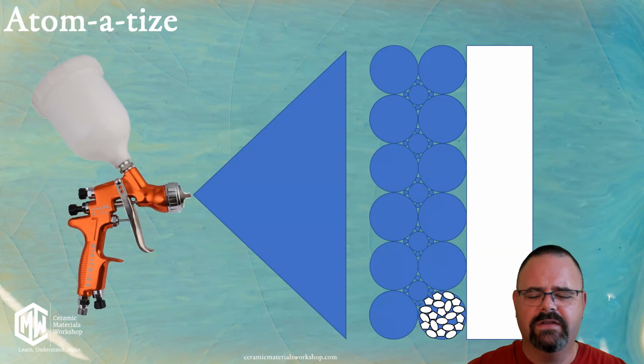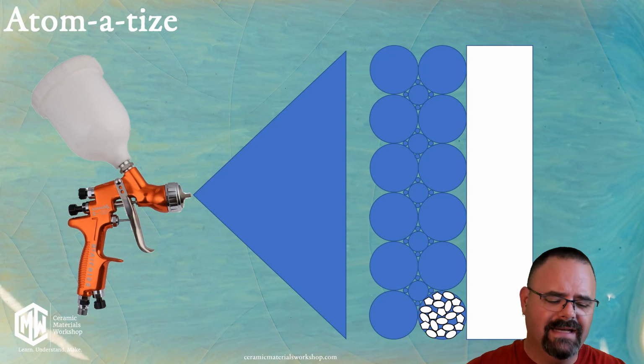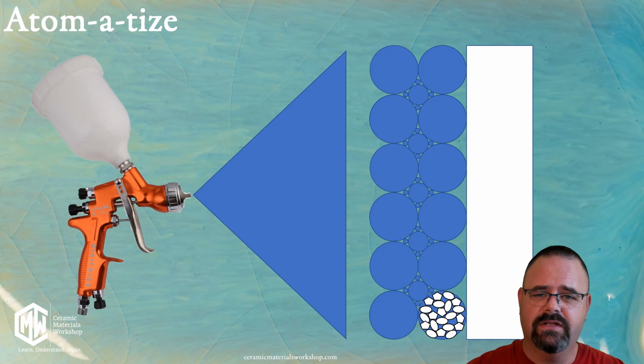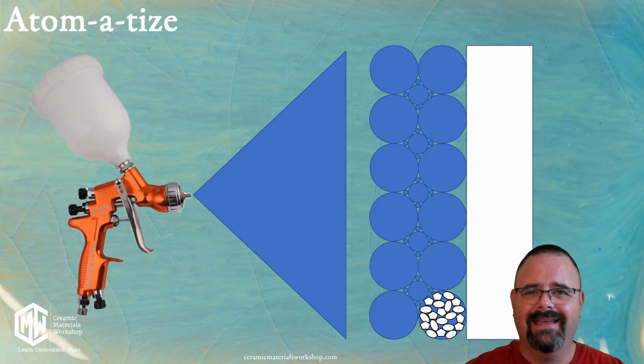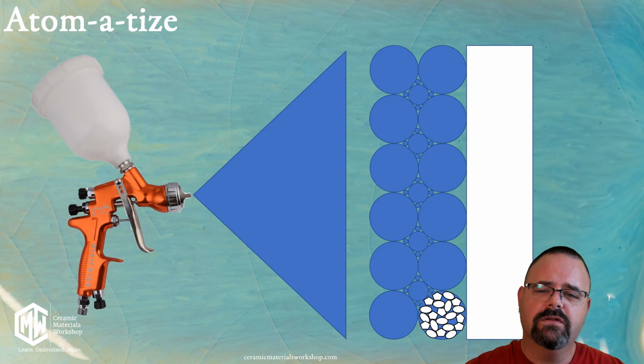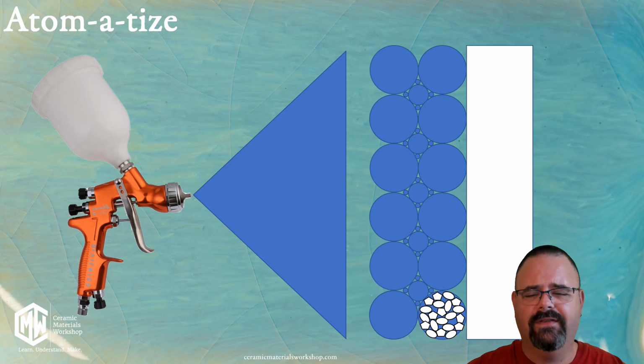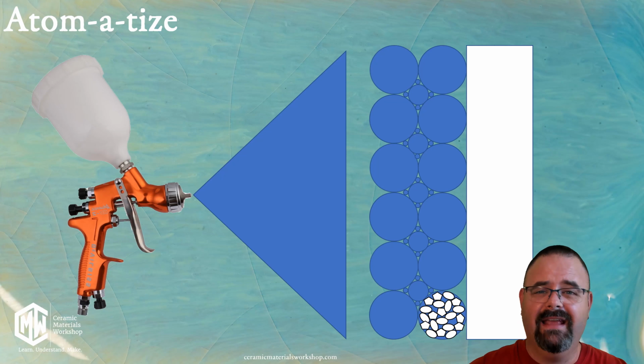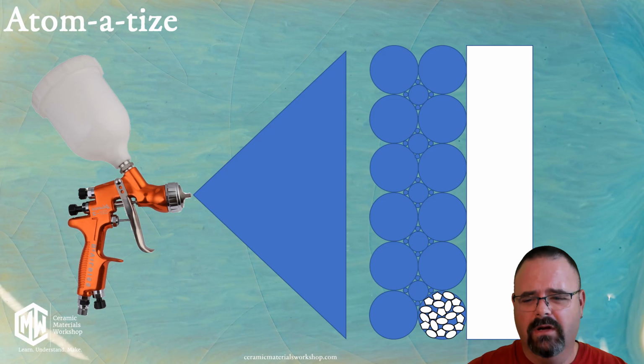There is also a spray application, and spraying tends to be the most rare in the arts, although it is commonly used in industry. It's used quite a lot. In a spray, we're taking the same liquid glaze, but then it's atomizing the particles. So it's turning the particles into little granules of individual glaze, little spheres, and those are thrown at the surface through the sprayer, and then they stick and give a quite good application because you get a lot of diversity of particle sizes. Spraying is wonderful, but there's not a ton to be said about it.